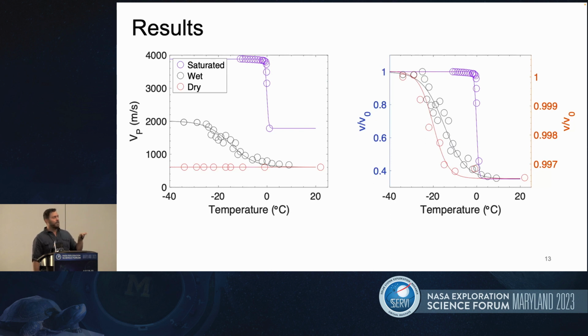And in fact, you do see some temperature dependence, even in the monolayer material. The difference is less than 1%, but it is measurable. And it showcases a further degree of freezing point depression than the polylayer adsorbed material. So that's sort of an interesting physics observation.